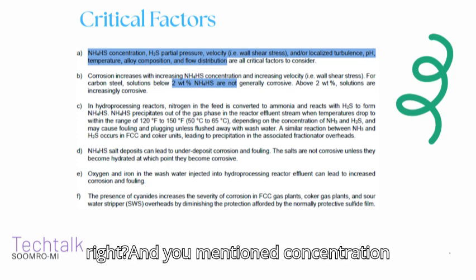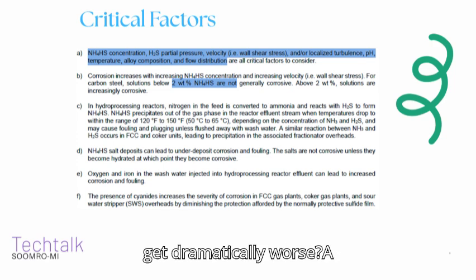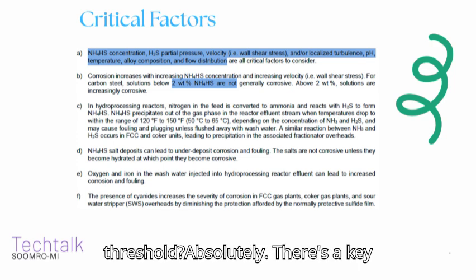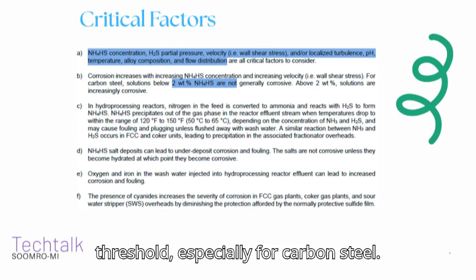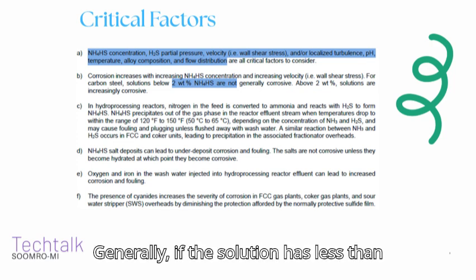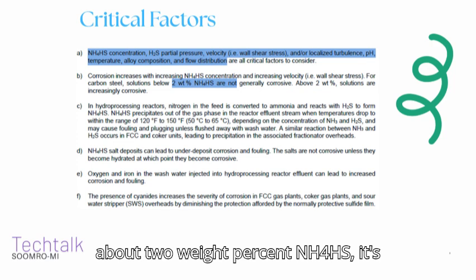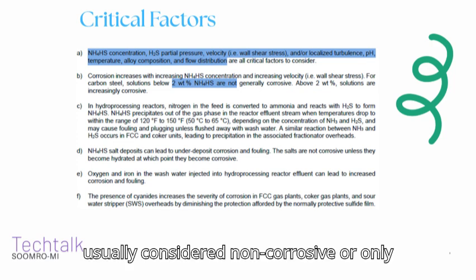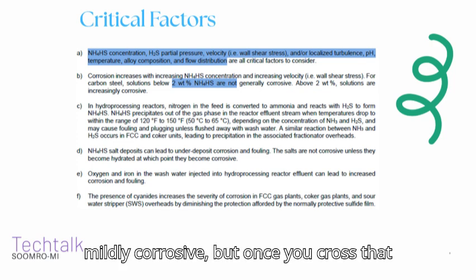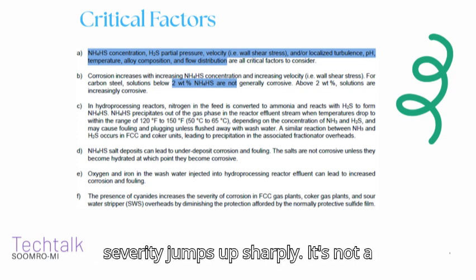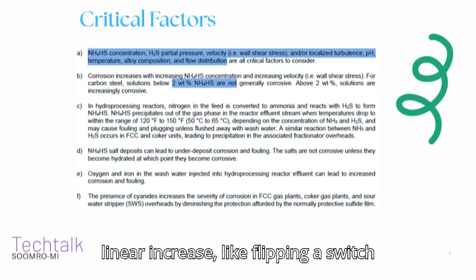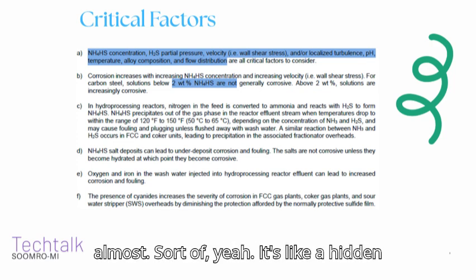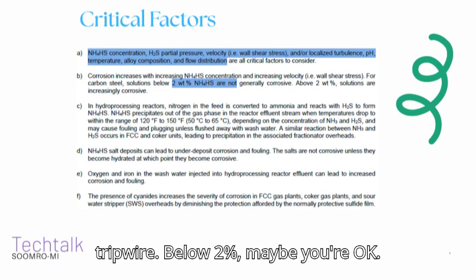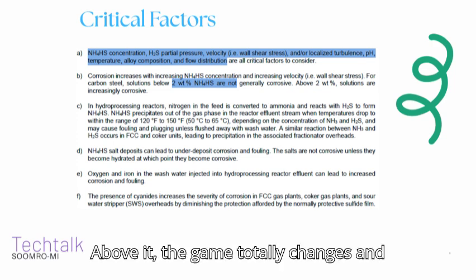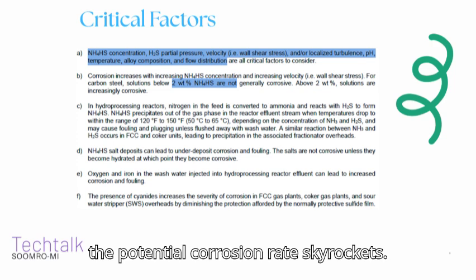Right, and you mentioned concentration earlier. Is there a point where things get dramatically worse, a threshold? Absolutely. There's a key threshold, especially for carbon steel. Generally, if the solution has less than about 2% NH4HS, it's usually considered non-corrosive or only mildly corrosive. That's good, 2%. But once you cross that 2% mark, the corrosion severity jumps up sharply. It's not a linear increase. Like flipping a switch almost. Sort of, yeah. It's like a hidden tripwire. Below 2%, maybe you're okay. Above it, the game totally changes and the potential corrosion rate skyrockets.